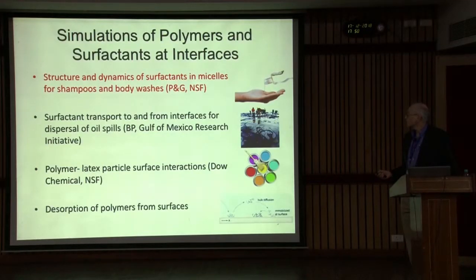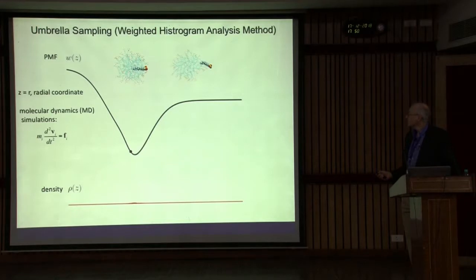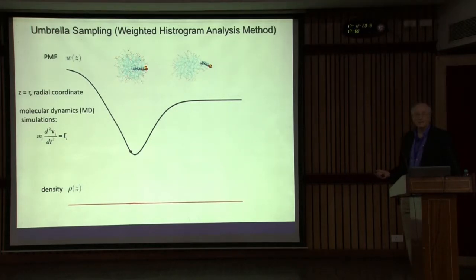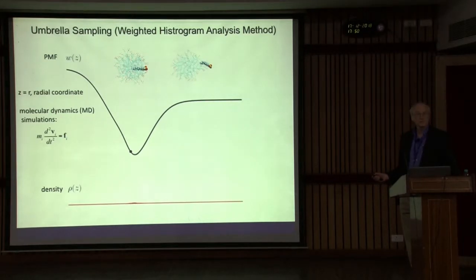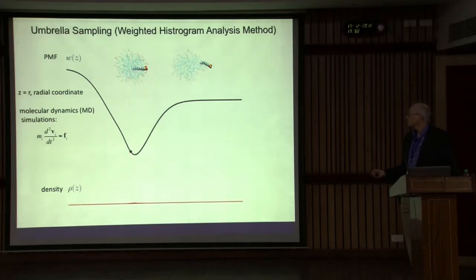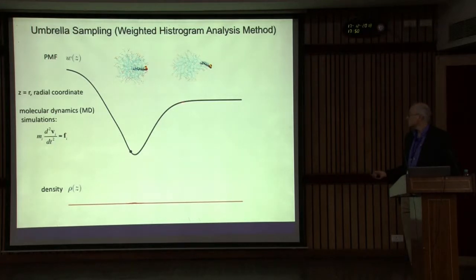We'll start with the first problem: structure first, then dynamics. If you're simulating a surfactant solution that forms micelles, the first dynamical problem you'd encounter is for a single surfactant to get out of the micelle so it can go into another micelle. At the atomistic level, you can simulate as long as you can afford, and this doesn't happen even once — you're stopped from the get-go. The reason is that the surfactant molecule is essentially in a free energy well: it's hydrophobic and likes where it's at, and to get out it has to diffusively climb a rather steep barrier.